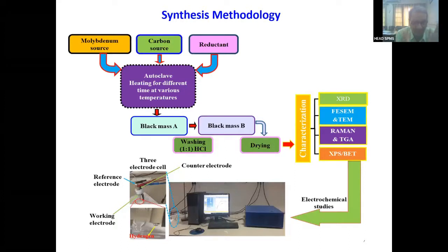So after completing the experiment, you have to switch off the furnace, let the autoclave cool inside the furnace, and take it out the next day. You will get some mass that is black in color. Because this mass contains magnesium oxide as a substance, you have to wash it with dilute HCl and then dry it. You are going to get nanocarbides here.